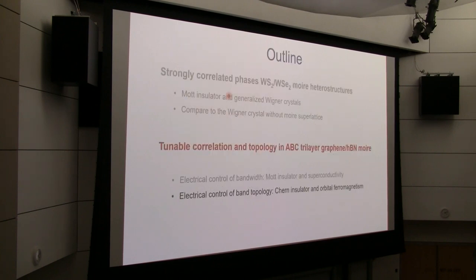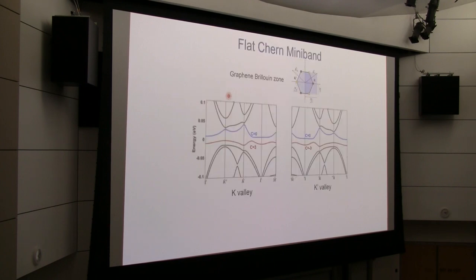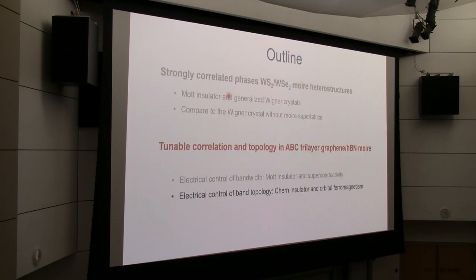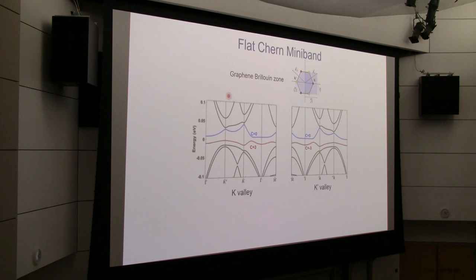So after we look at this trivial band, we can ask, what happens when you have a topological side? That means we look at negative electric field. One thing I need to remind you is, with graphene, there are always two valleys. So when I say the Moire miniband is topological, actually there are two copies of them, one at k and one at k prime. Because they are a time reversal pair, they have exactly opposite Chern numbers. So if you have a charge neutral system, for example, the total Chern number equals 0. Or if you start to dope holes in the system, the holes can sit in both bands. And if they are equally distributed in these two bands, it's not that interesting.